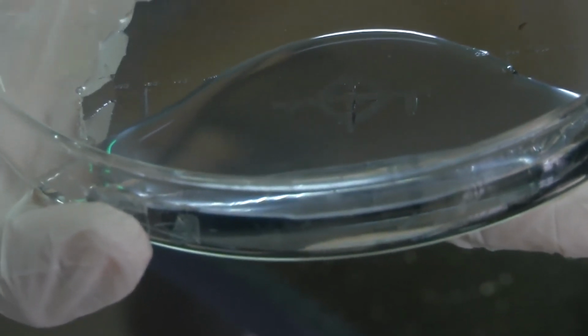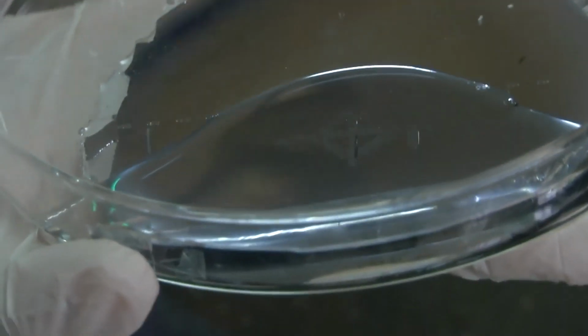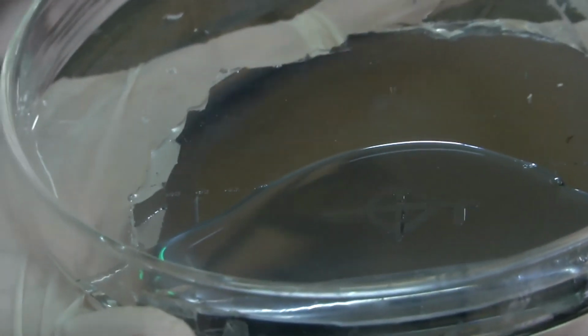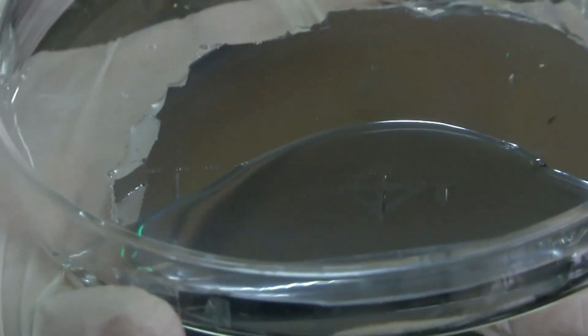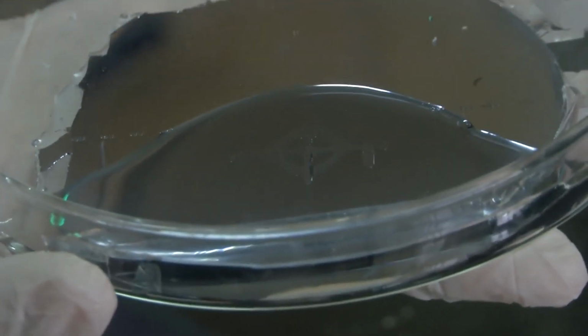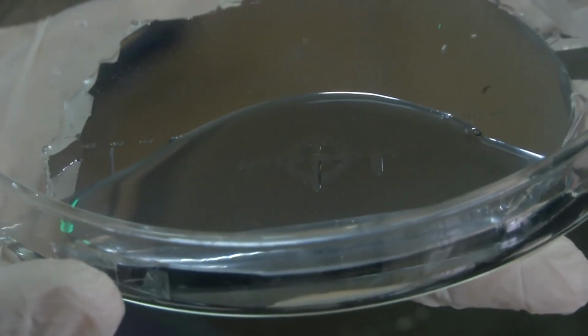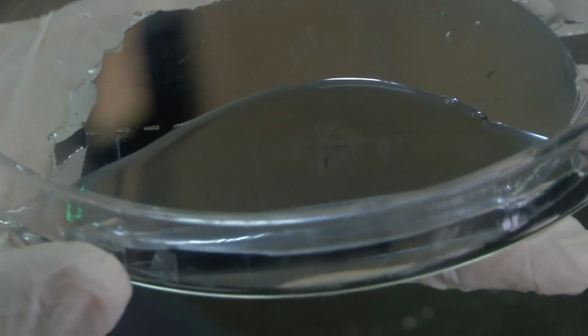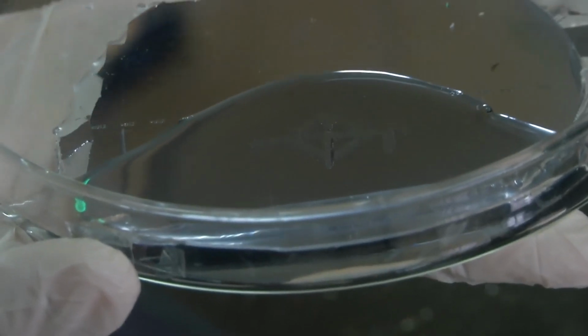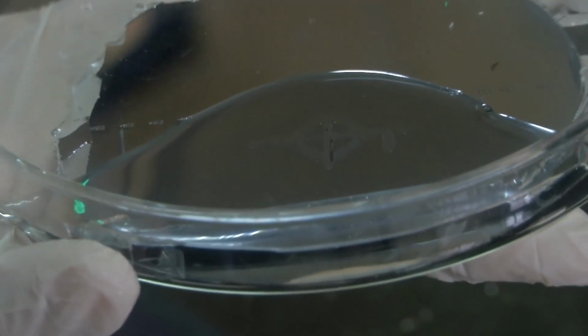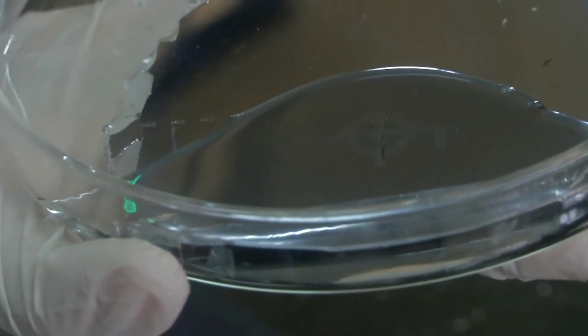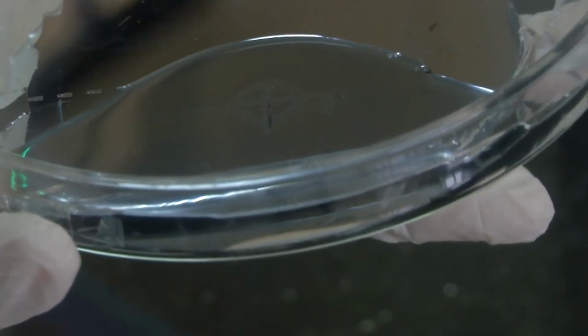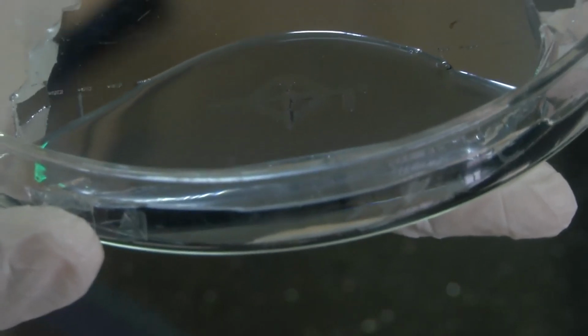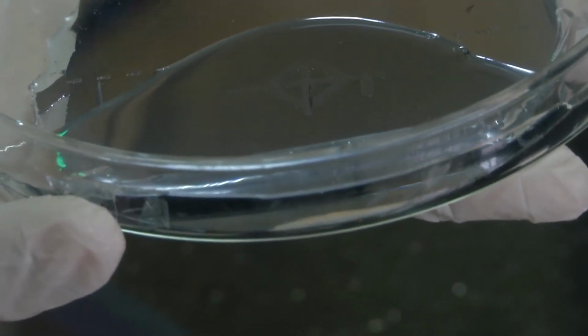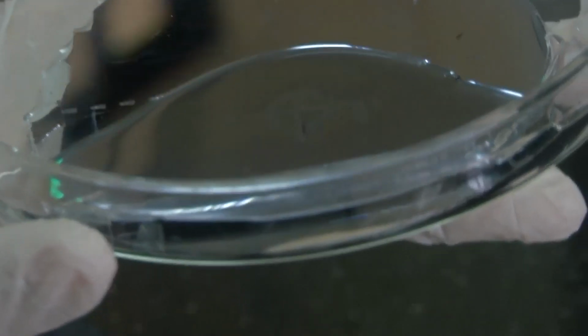substrate. Another thing you have to take care of while you do this process is to make sure the substrate is thoroughly cleaned. You can follow this procedure: clean it with acetone followed by IPA and then some DI water. Be it the silicon substrate or any other substrate on which you want to fabricate the device, follow the cleaning procedure and then have the PDMS liquid poured onto the device.